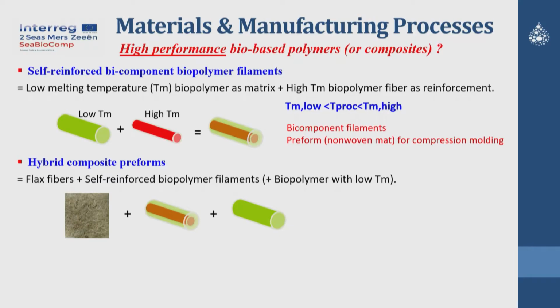And for the second one, why not add a secondary reinforcement such as flax fibers. So flax fibers, biopolymers, every component is bio-based. Another advantage is that due to the high stiffness and strength of flax fiber, we can further enhance the mechanical properties. This is a kind of ternary composite with two kinds of reinforcement at the same time. And we also developed non-woven preforms ready for compression molding.